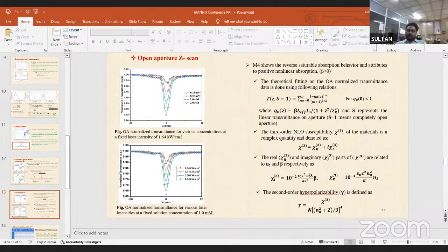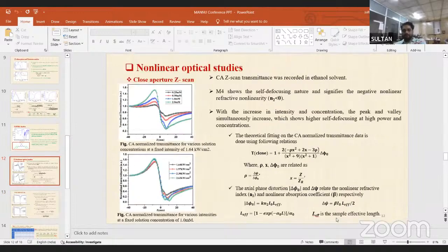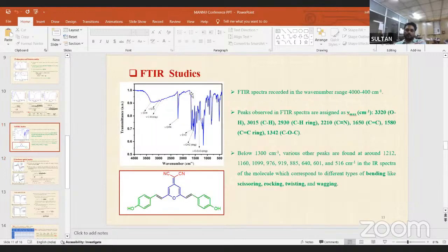We have also calculated the third order nonlinear susceptibility, whose real part is related to nonlinear refraction and imaginary part is related to nonlinear absorption. We have also calculated the hyperpolarizability using this relation manually. And for optical limiting, because our molecule shows reverse saturable absorption, our molecule can act as an optical limiter.